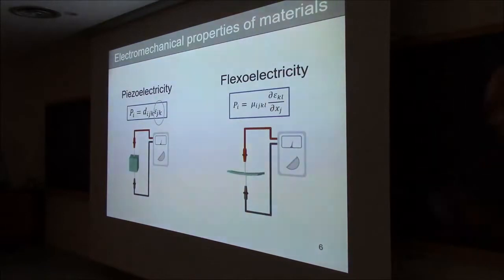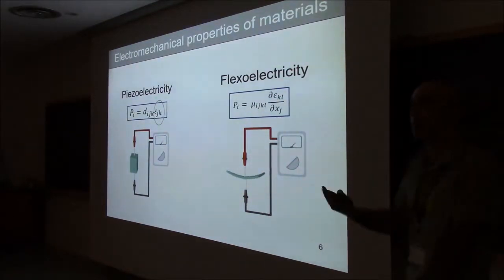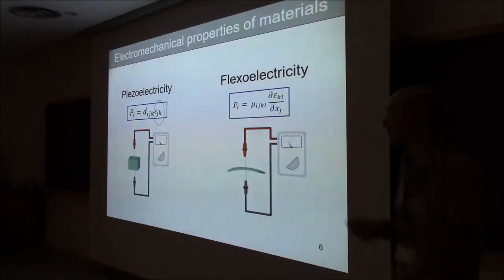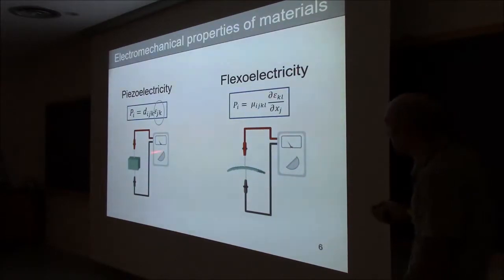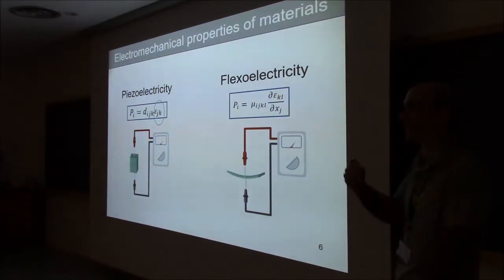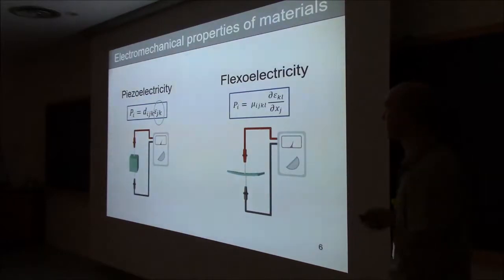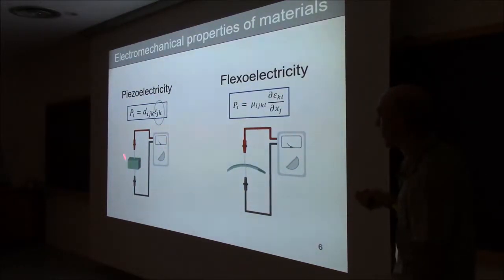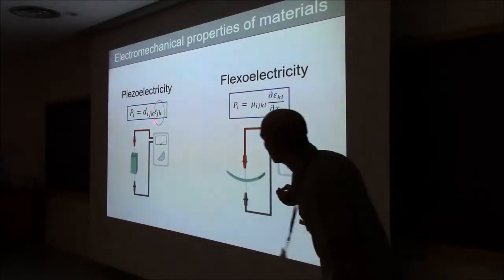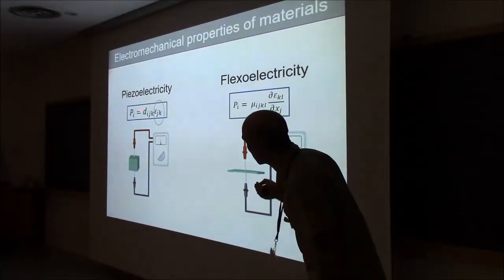That's kind of the symmetry principle as to how you measure the two things, piezoelectricity versus flexoelectricity. Well, it's quite simple. If you have a piezoelectric material, something that is asymmetric to start with at the lattice level, then you just apply a homogeneous deformation and you will get a polarization. Okay? And the amount of polarization will be given to you by the piezoelectric tensor.